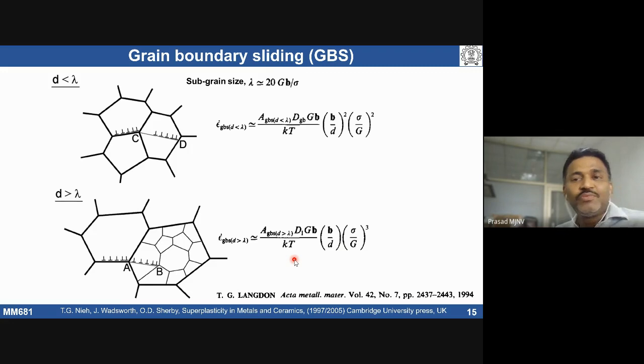Now assume that I'm defining a material at a stress of 50 MPa. I know the shear modulus of the material and the Burgers vector. Then I can calculate the lambda value. It happens that the subgrain size is going to be coarser than the superplastic material grain size. So grain boundary sliding takes place not only in fine grain, it can also happen in coarse grain materials. Superplastic materials should have a fine grain size, and when I say fine grain size, it should be equivalent to or less than the typical subgrain size it can develop.